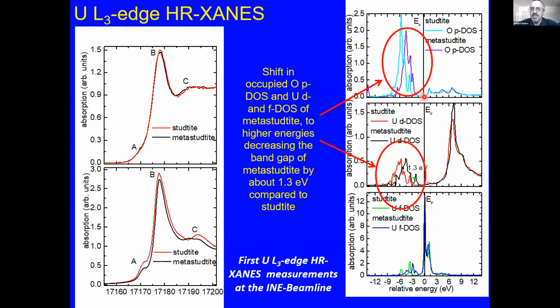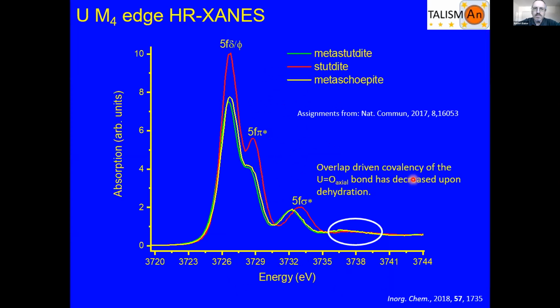And what's really nice is that we do see a change in both the oxygen and the uranium D and F orbitals when we remove those waters of crystallization. And the change is 1.3 eV from the theory, which is pretty comparable to our experimental results. But what's even nicer are the M-edge spectroscopy. So we can clearly see 3 transitions, which can be assigned to the transitions to the 5f orbitals in their delta and phi types, the pi star, and then the sigma star orbitals.